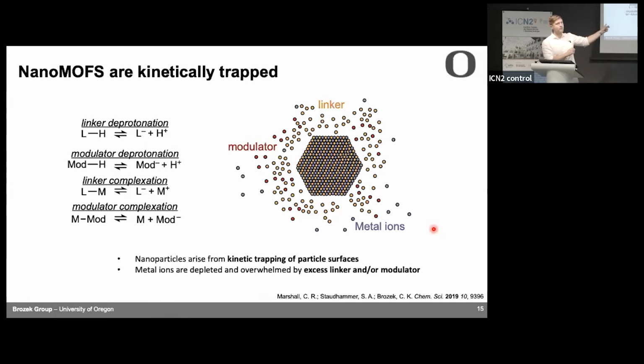The last slide I showed was showing that we can make the zinc version of that MOF. It turns out the only way to make small particles of the zinc version is to start off with zinc oxide, which is a really weird precursor, not zinc acetate, not zinc chloride. Those make particles that are way too big. I think what you need is something like zinc oxide that very slowly releases zinc, and then the ligand modulator will kind of trap it, and then you get small particles.